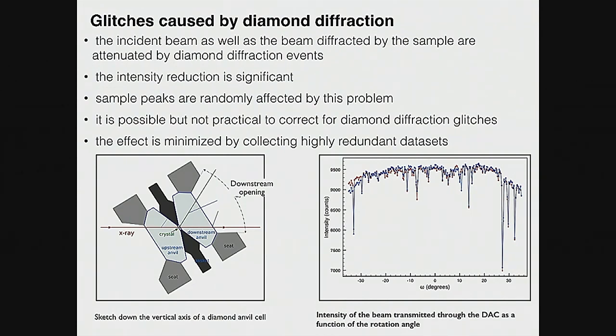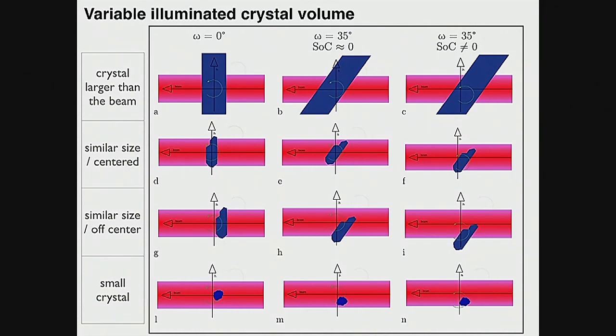Again, it depends on the problem you're chasing. Recently, I had to refine a beryllium position in an yttrium compound. So of course, I know I need really good data to nail down that problem. Some other problems, you can live with these glitches. There's a little bit of noise in your data, but they can be as high as 20% of intensities, and they're still manageable. The biggest problem, and this applies to several microdiffraction techniques, is